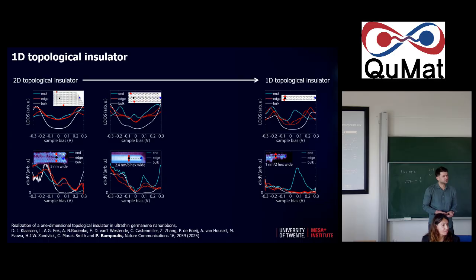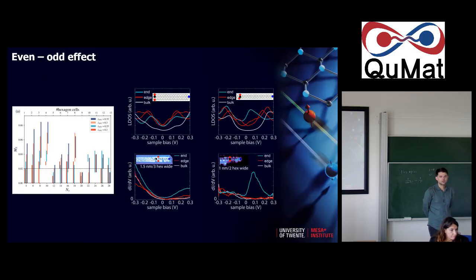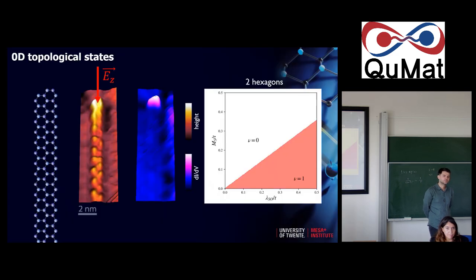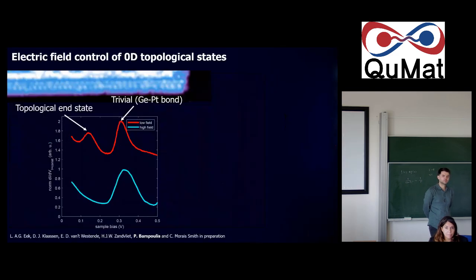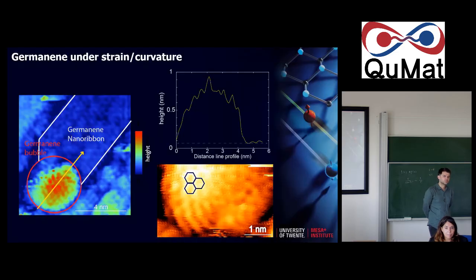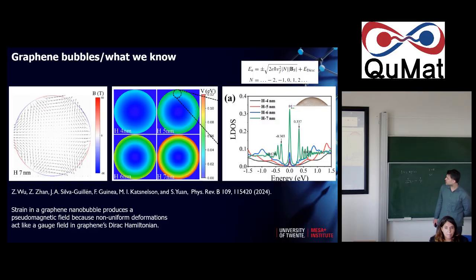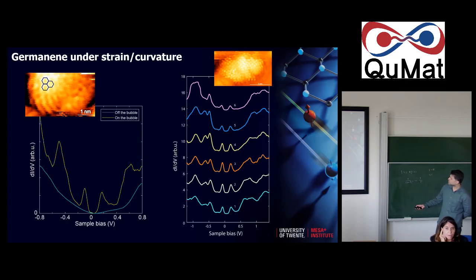Maybe a very naive question about the last part on the nanoribbons. You mentioned that the gap and the two peaks are not fully symmetric around zero energy. Is that really expected in these cases? We think that it's, you mean this, right? Yes. So this is a little bit closer to zero, this a little bit further away. It also matches this. This is the same sample that I showed you the data on nanoribbons, and the peak is also more towards the positive side.